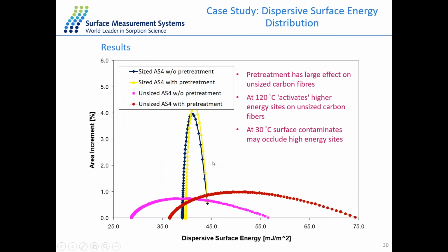We've also done a point-by-point integration to obtain the dispersive surface energy distribution. What we can see is that the wider the peak width, the more heterogeneous, and the narrower the peak width, the more homogeneous. So in this case, if we have a look at the temperature differences, we can see that once we increase the temperature of our carbon fibers to 120, this is actually removing any kind of adsorbates or anything blocking high energy sites, exposing these energy sites when we do our experiment. At 30 degrees, this isn't enough energy input onto the surface of the samples, and we cannot remove these adsorbates. As a result, if we look at these two peaks here, we have a much wider peak width at 120 degrees and a much narrower peak width for 30 degrees.